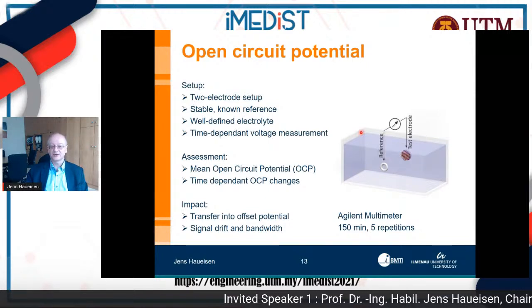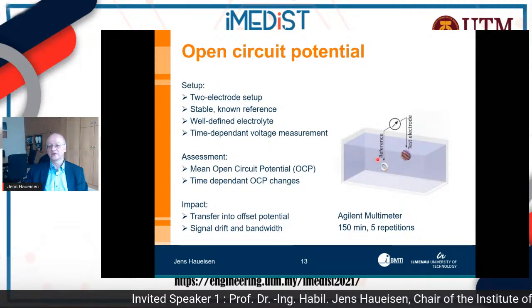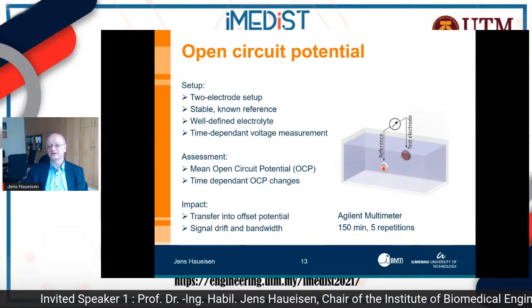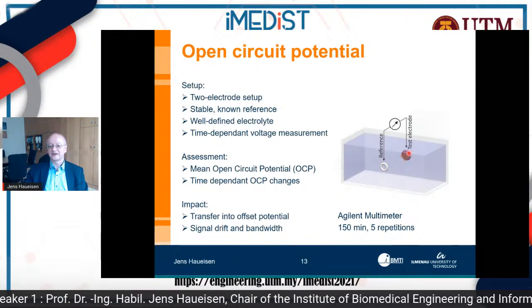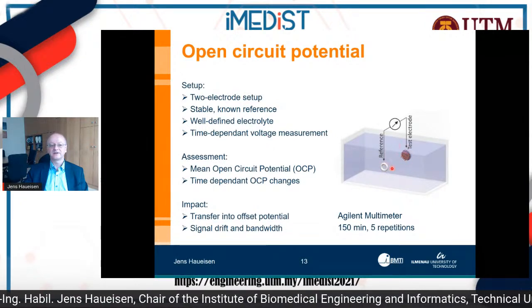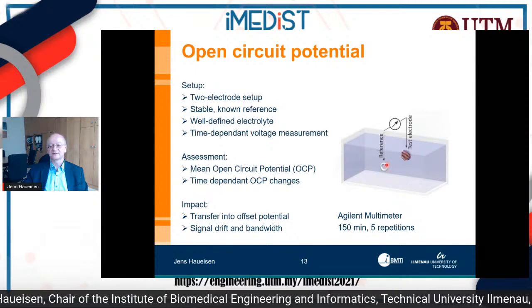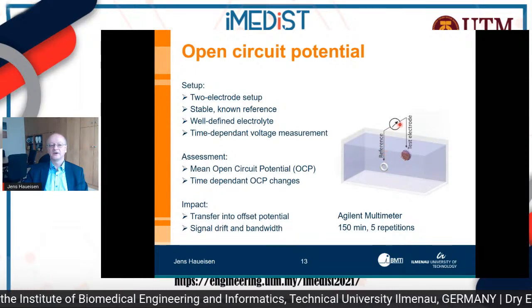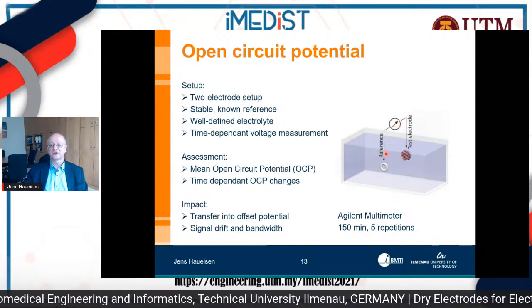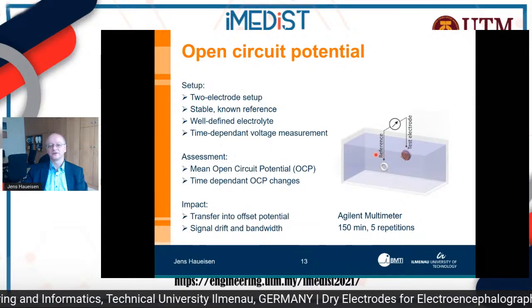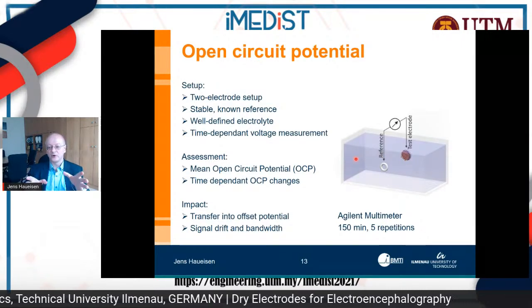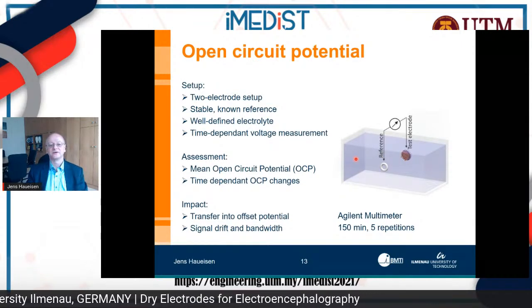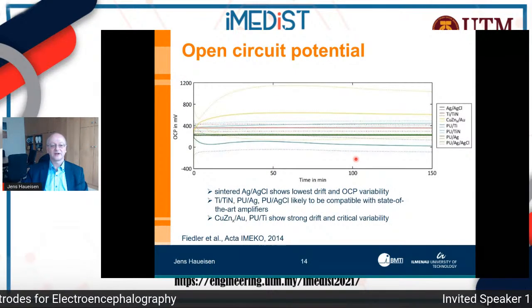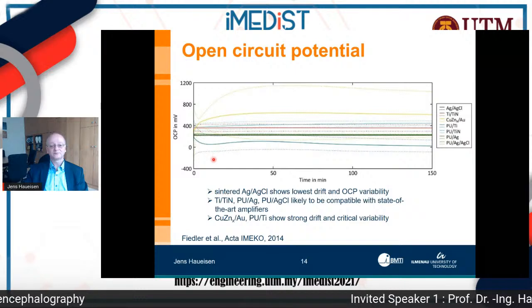So how is this measured? You have a reference electrode, which is a standard electrode, as you can see here. And you have your test electrode. And again, they're located in a bath. But this time you just measure with the multimeter the potential which actually occurs once you immerse the electrodes into the bath.